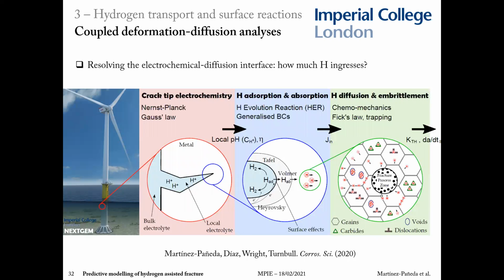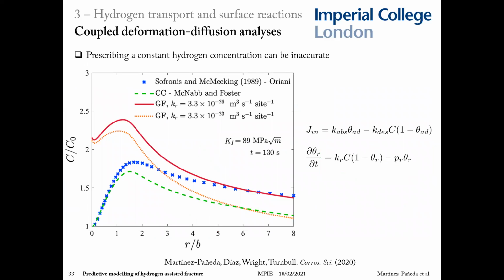And another important aspect that has to be addressed to properly quantify hydrogen is to adequately characterize hydrogen ingress into the metal. This is not complicated for gaseous environments. One can just make use of Sieverts' law, but in aqueous environments, the physical picture is more complicated. And what I've been working on with Alan Turnbull is in developing generalized boundary conditions that can resolve the electrochemistry diffusion interface.